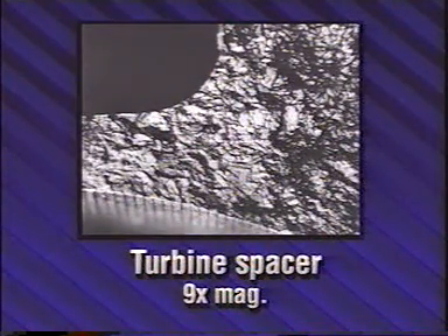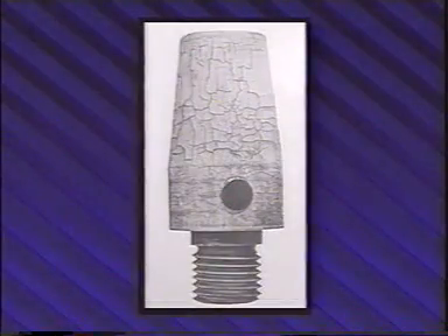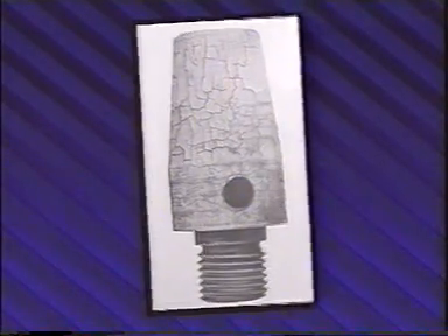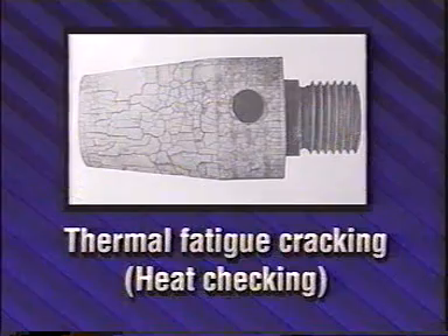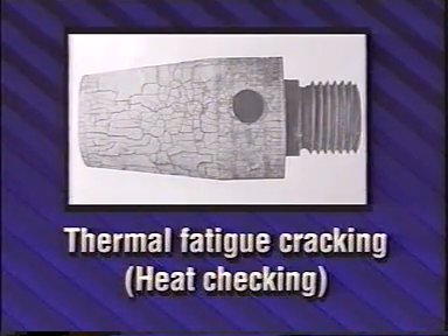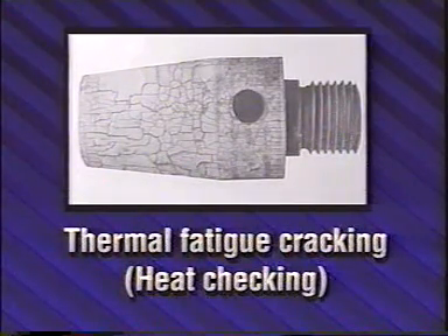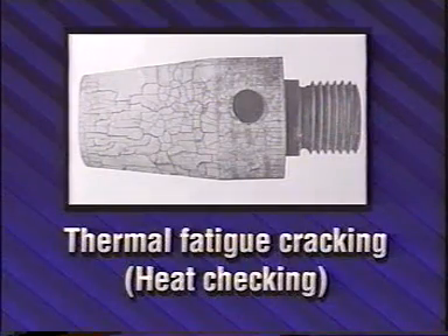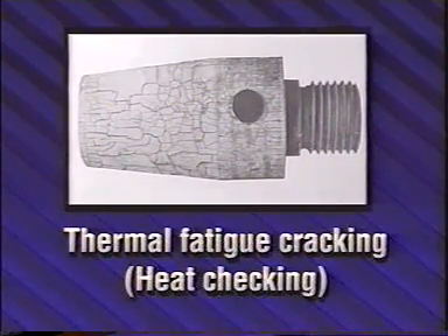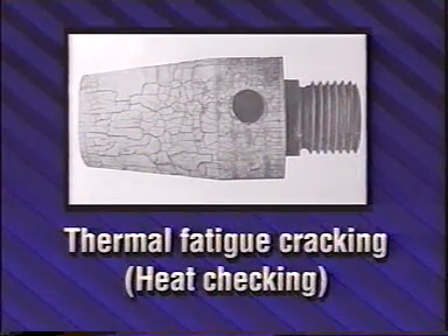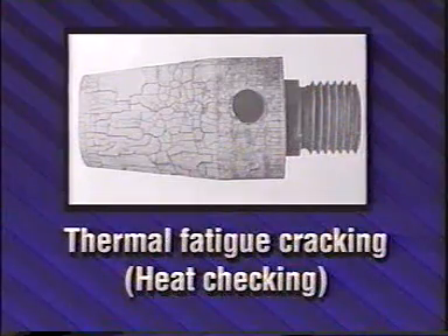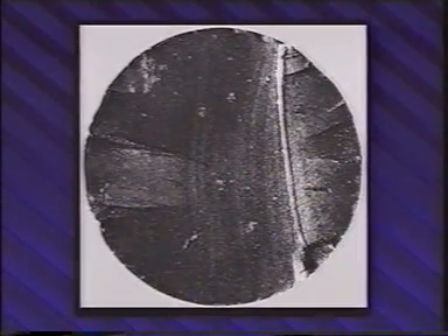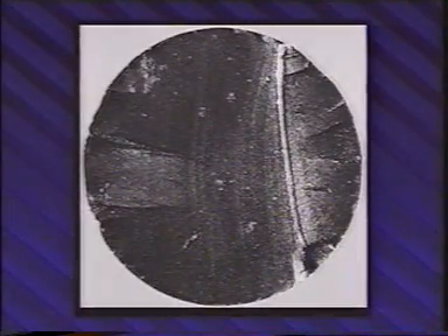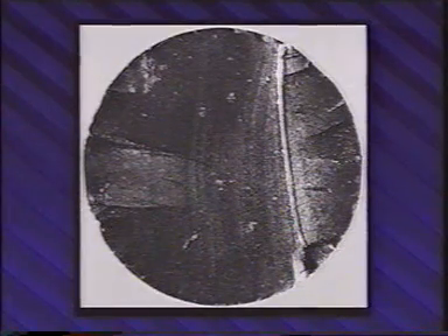usually progressing transgranularly. Because thermal fatigue cracks initiate externally, the amount of corrosion or oxidation varies along the fracture surface. The amount of corrosion or oxidation is inversely proportional to the depth of the crack. Oxidation in stress rupture cracks is more uniform. Excessive creep produces considerable distortion and numerous subsurface cracks. Thermal fatigue, on the other hand, produces little or no distortion and relatively few surface-oriented cracks.